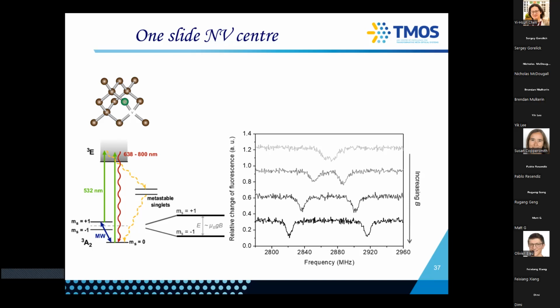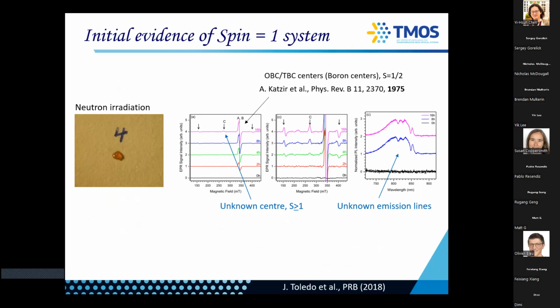Not sure. Okay, so the question was, well, can you find a spin defect in hBN? And so here we go back to 2018. I was visiting the group in Brazil because UTS has a collaboration with a group in Minas Gerais, I think it's called. And the only thing they have, and they do it really, really well, is neutron irradiation and EPR. And so we took an hBN and we neutron irradiated it, and it became pink. This is not a false color image. It is actually real hBN, real optical image, become pink.